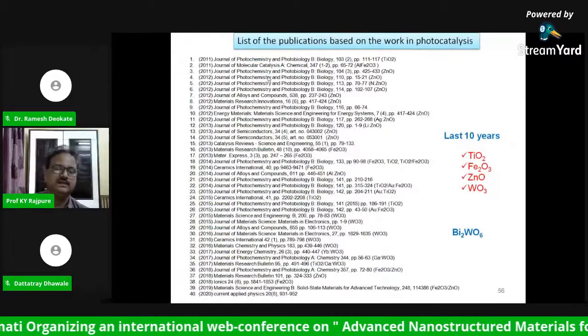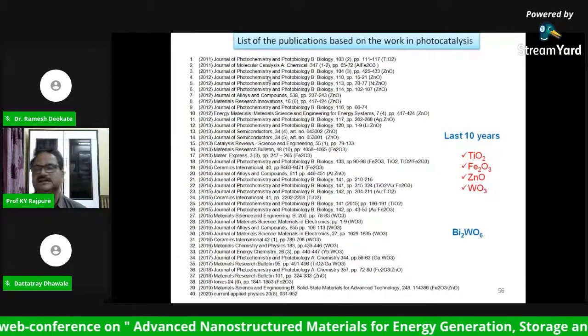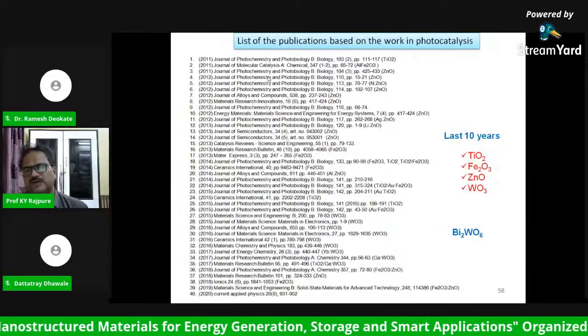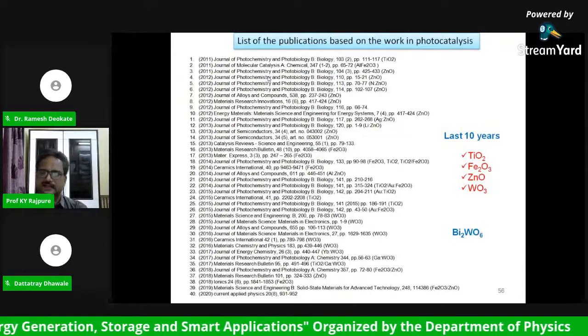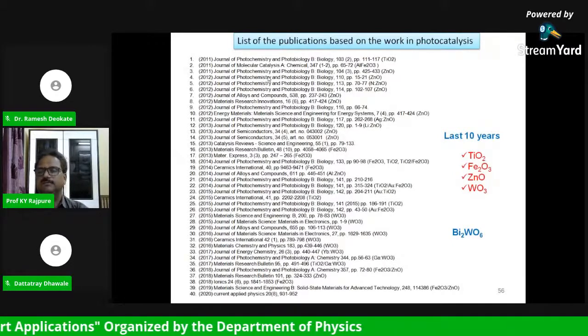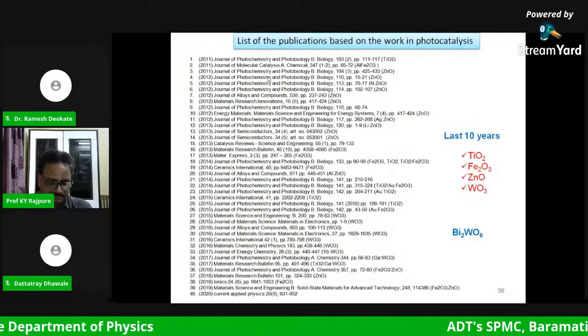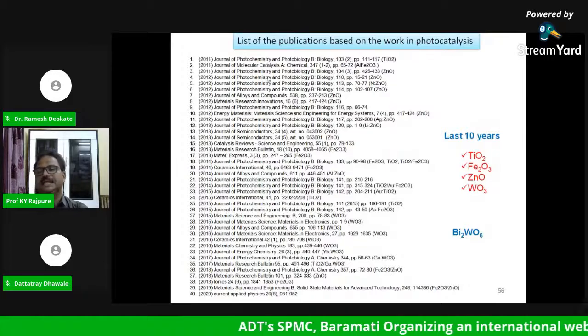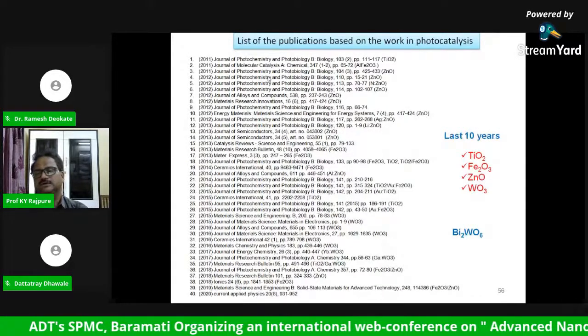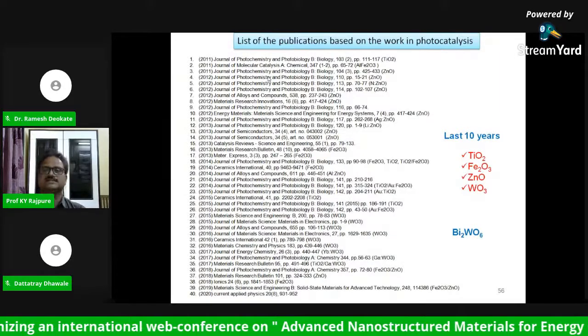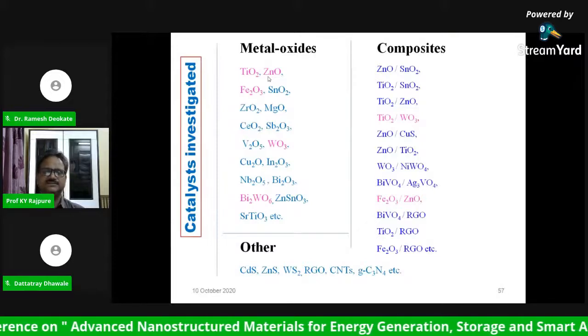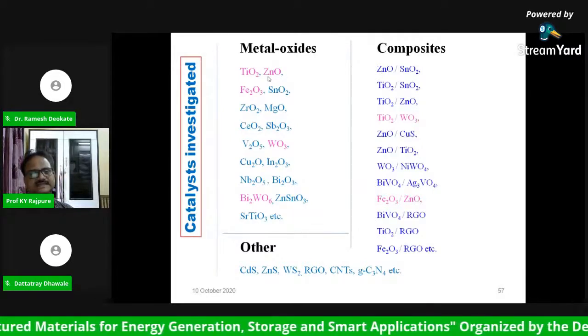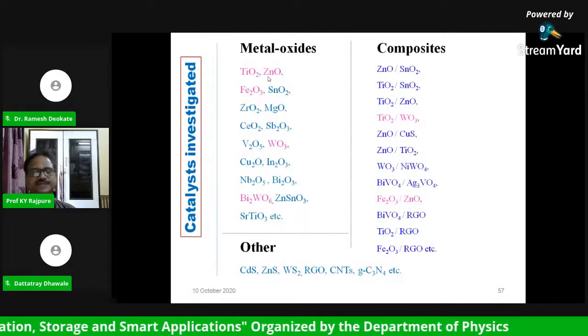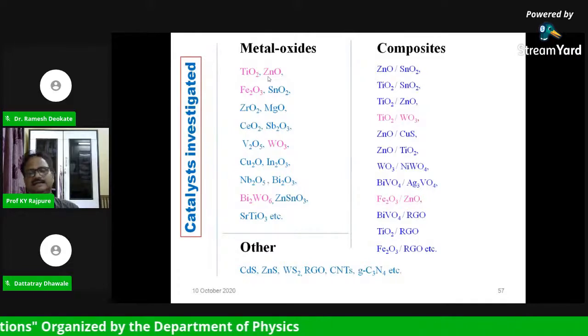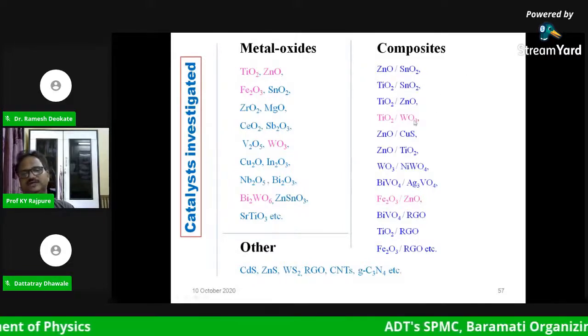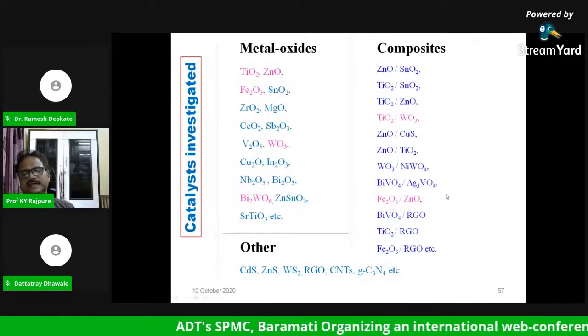And this is the list of the papers which were reported and published in the last 10 years on photocatalysis. We have used TiO2, iron oxide, zinc oxide, tungsten trioxide, their composites, their doping, their nanostructures, by a variety of chemical methods. Our current efforts are focused on preparing ternary oxide thin films like bismuth tungsten oxide for photocatalysis. And this is the list of the catalysts investigated: TiO2, zinc oxide, iron oxide, tungsten trioxide, which we already tried. And the composite between TiO2 and tungsten trioxide, the composite between iron oxide and zinc oxide, and others we have already tried.